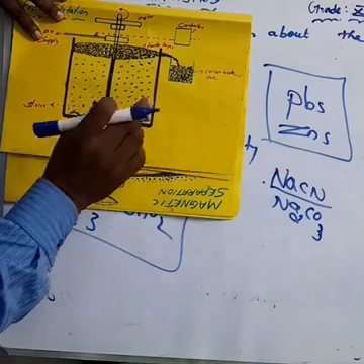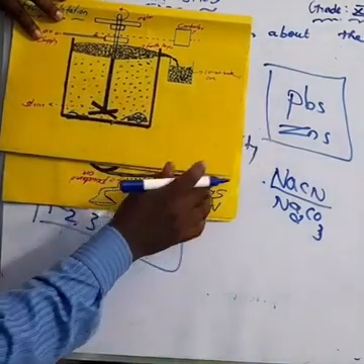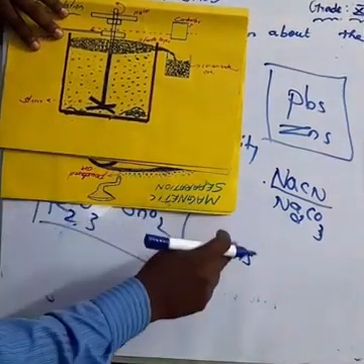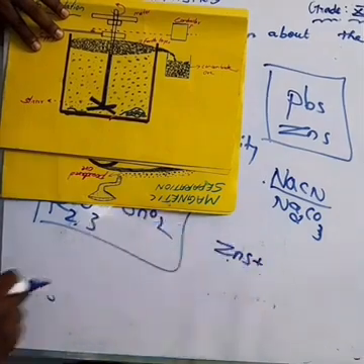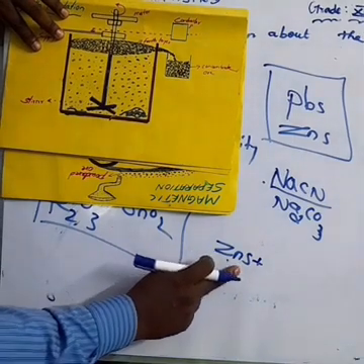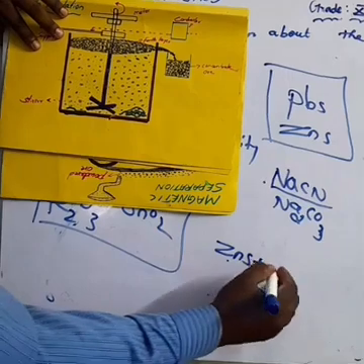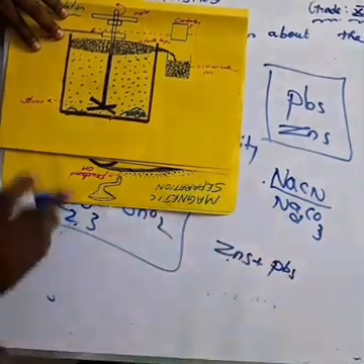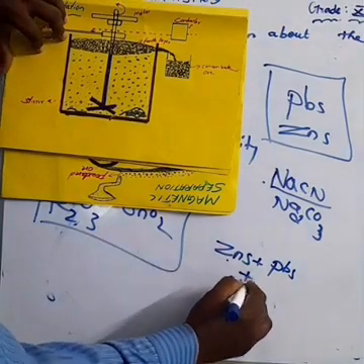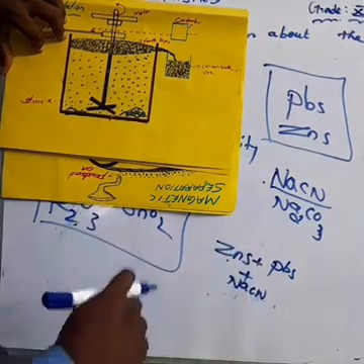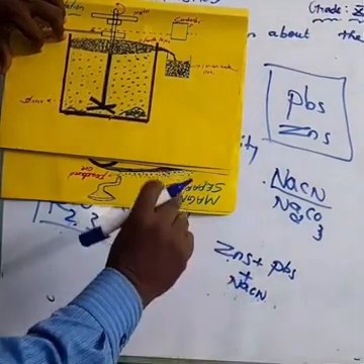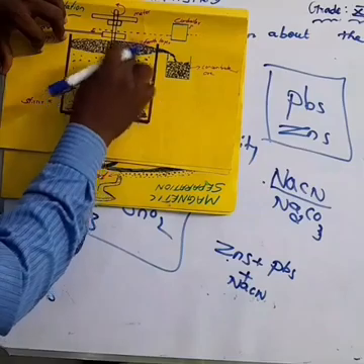For example, when an impurity such as zinc sulfide is present in galena. What is the formula for zinc sulfide? ZnS, zinc blende. Don't forget that. Present in galena. What is the formula for galena? PbS, lead sulfide. Here, sodium cyanide, NaCN, is added to depress the flotation property of zinc sulfide by forming a layer of zinc complex. Can you understand me?